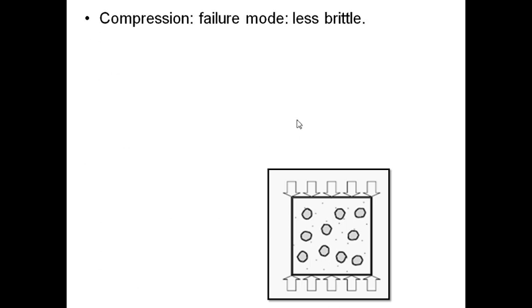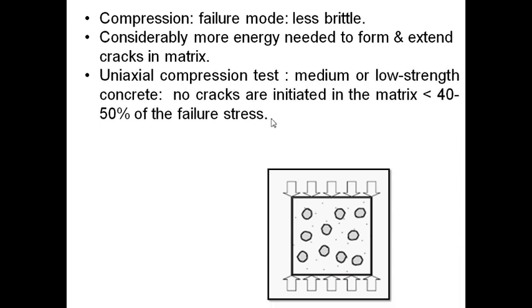The compression failure mode is less brittle. Considerably more energy is needed to form and extend the cracks in the matrix. For uniaxial compression test, medium or low strength concrete when tested, no cracks are initiated in the matrix for less than 40-50% of the failure stress. That means when the stress reaches 40-50% of the failure stress, no cracks are initiated in the matrix for medium or low strength concrete.